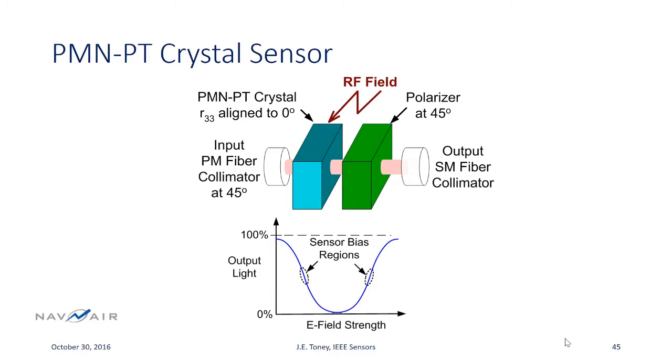And one more program that we had, sponsored by NAVAIR in China Lake, was to look at an alternate material called PMN-PT. It's called a ferroelectric relaxor material. Its advantage is it has a huge electro-optic effect, like an order of magnitude higher than lithium niobate. Disadvantage is it also has an order of magnitude higher dielectric constant, so it's not clear whether those two things are a wash. But this was actually a bulk sensor, just based on polarization rotation.